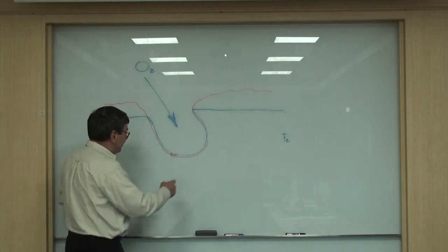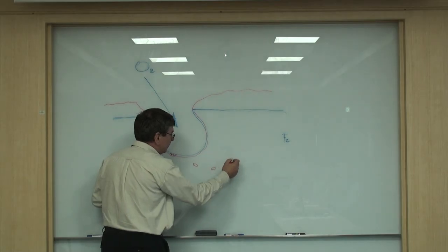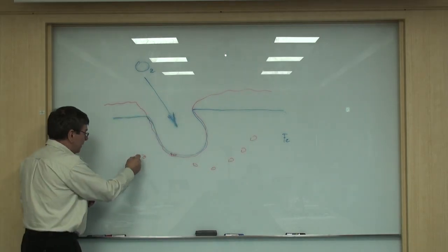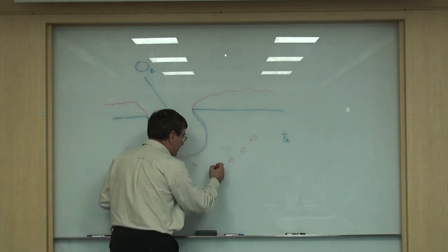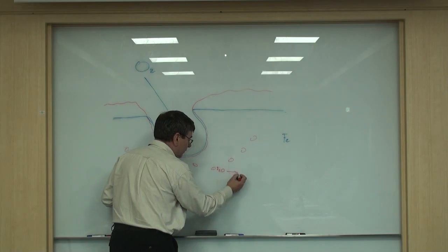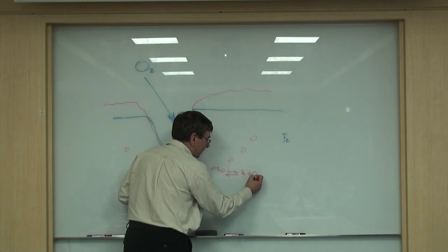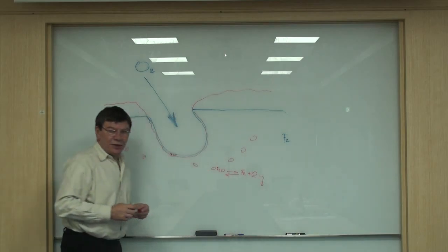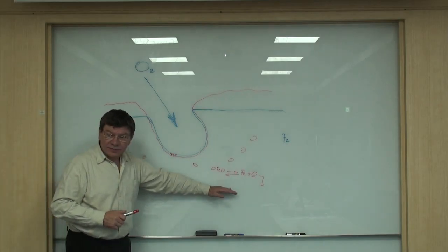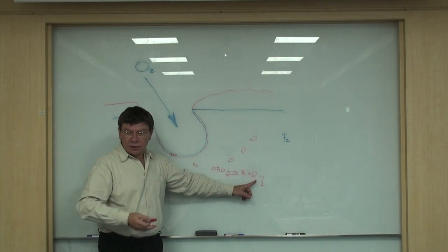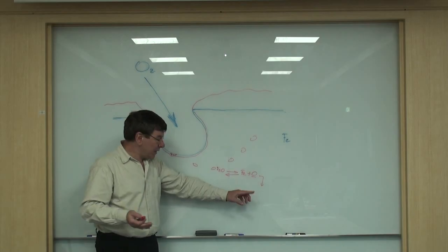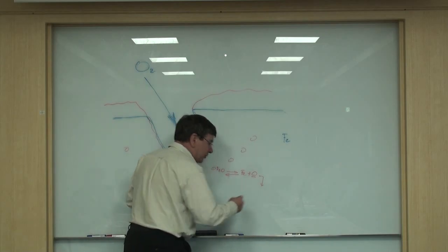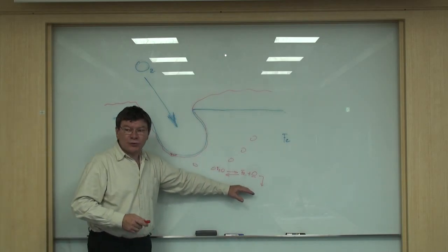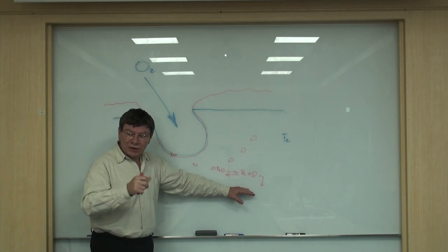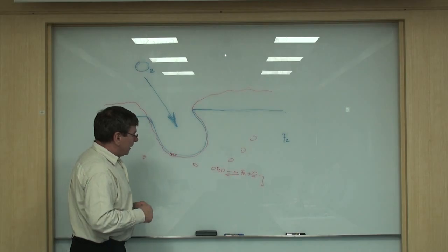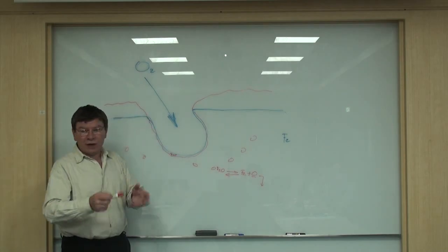Okay? And then due to the bath movement, this iron oxide is migrating into the steel. And then you have a reaction, FeO, Fe plus oxygen. This oxygen is going to get dissolved in the steel. And the oxygen solubility is, let's say, proportional to the bath temperature and also influenced by the sulfur, because the sulfur solubility in the steel is occupying more or less the same location as the oxygen. And this dissolved oxygen is going to realize the decarburization later.